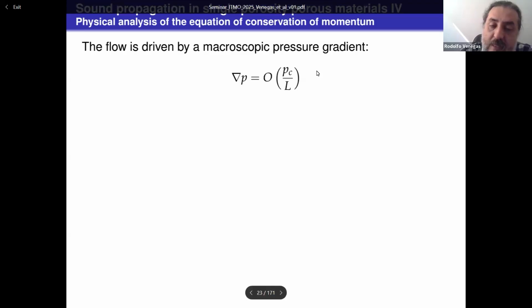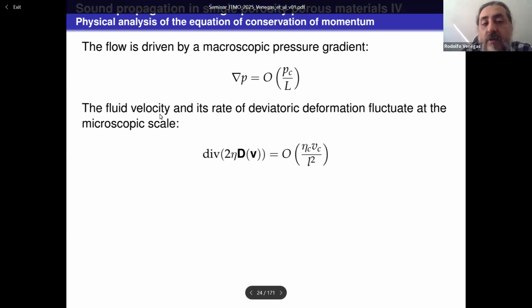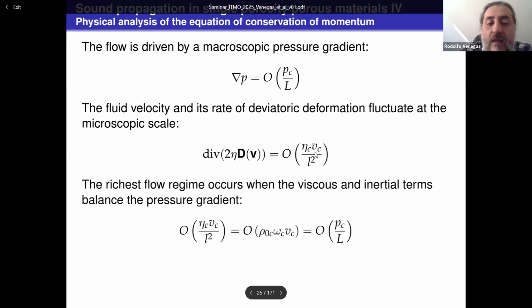So we see that the flow is driven by a macroscopic pressure gradient. An estimation of this macroscopic pressure gradient is P_C over L, where P_C is a characteristic value of the acoustic pressure, and L is the macroscopic characteristic length. Also, the fluid velocity and its rate of deviatoric deformation fluctuate locally, so we can estimate this term in this way. And we're interested in the case where all the terms in the Stokes equations are of the same order of magnitude, so that we can capture viscoinertial effects.